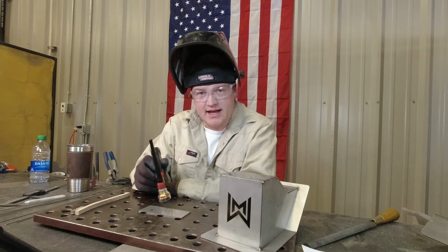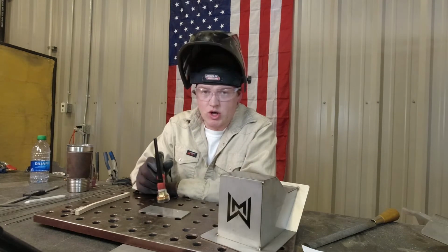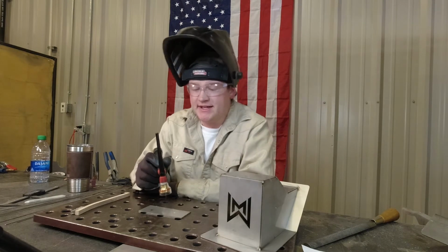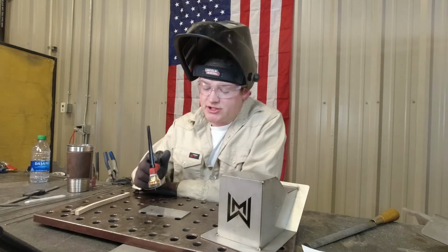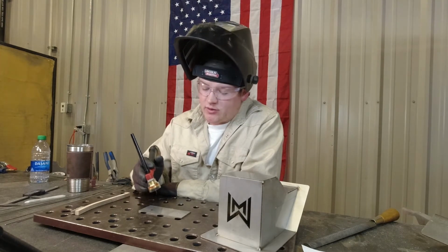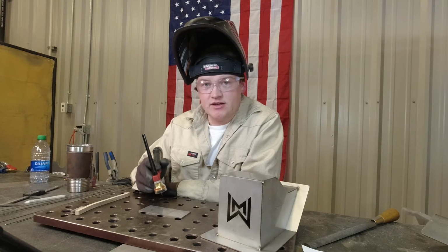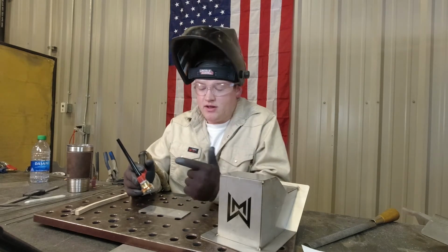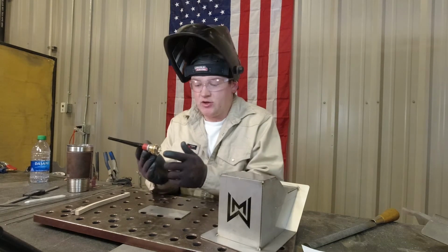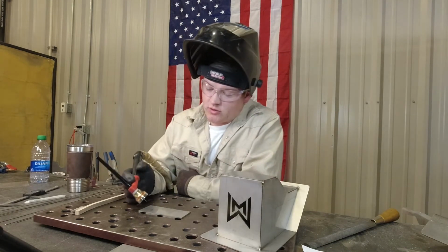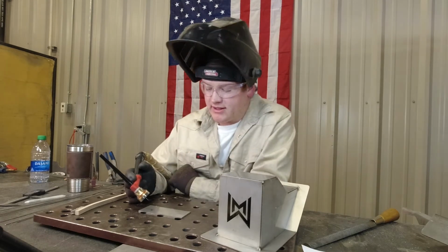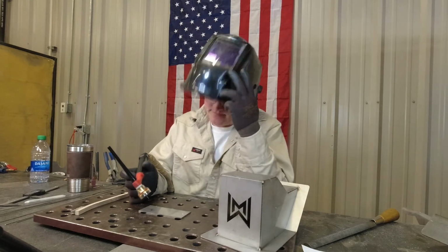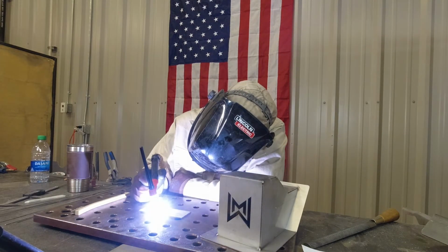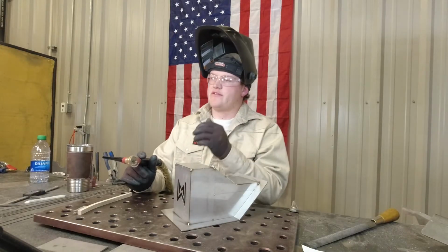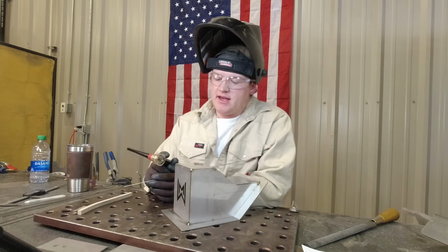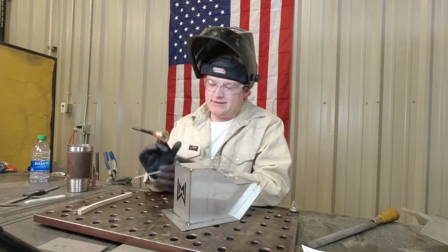And if that tack at any time turns gray, blue, dark gray, or anything like that, that means that your shielding gas is turbulent. That means it's coming out, grabbing oxygen out of the atmosphere and putting it in your weld pool. And right off the bat, we're going to know that you need to fix your gas pressure, your gas cup setup, or your tungsten stick out. You can have your tungsten sticking out too far. So just do this quick little test and make sure that your gas pressure and your cup and everything is set up just right. Make sure you have a post flow and a pre-flow set on your machine, and make sure your gas settings are set properly, and we're ready to weld.